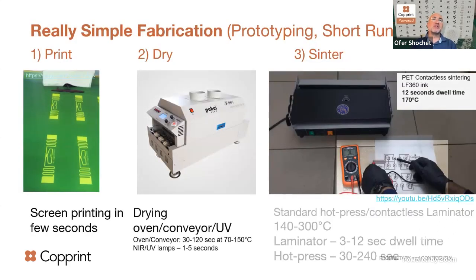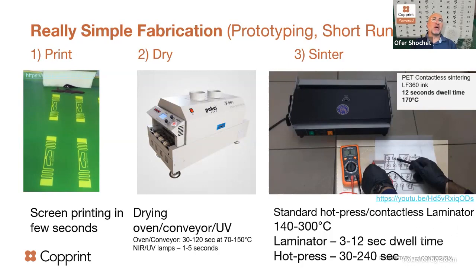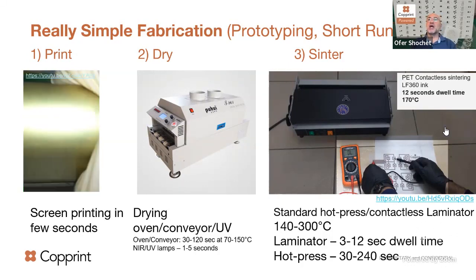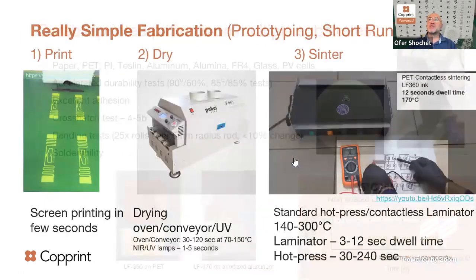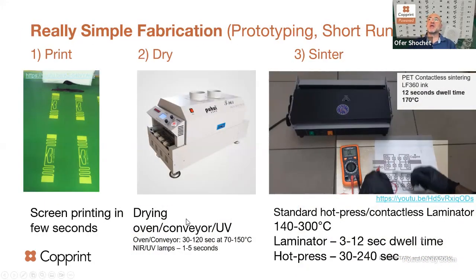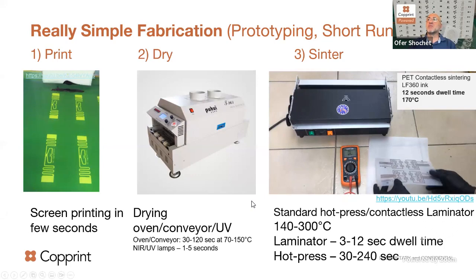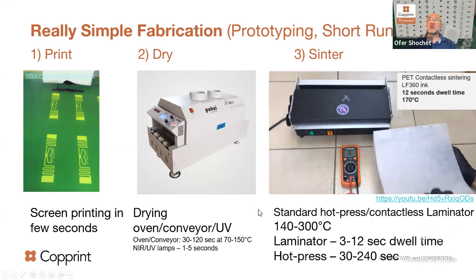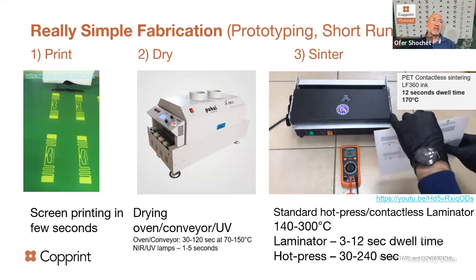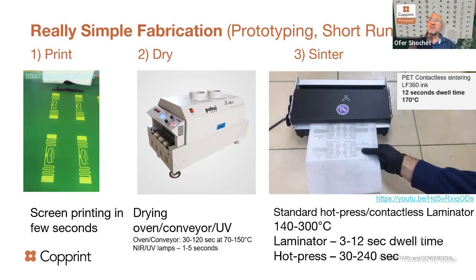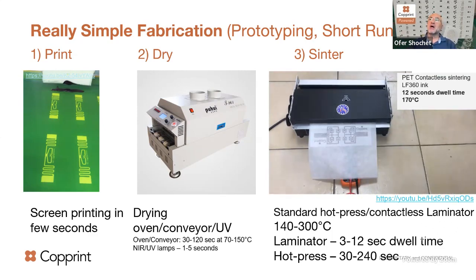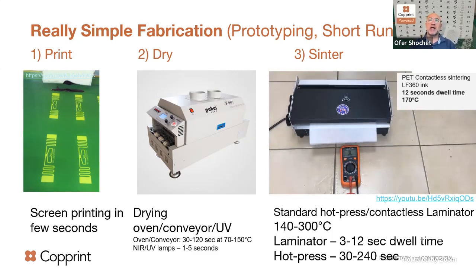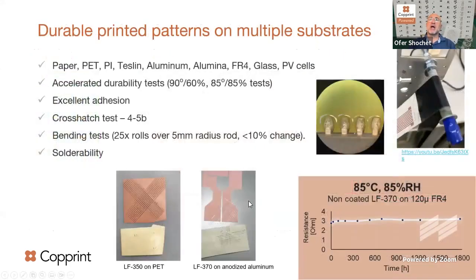So our process is very simple. You can see it on our website for simple printing, and then a short drying, and then a very simple process to do the sintering. I will go very quickly, just printing, putting it in an office laminator that costs $200, and then you get a conductive pattern after that.